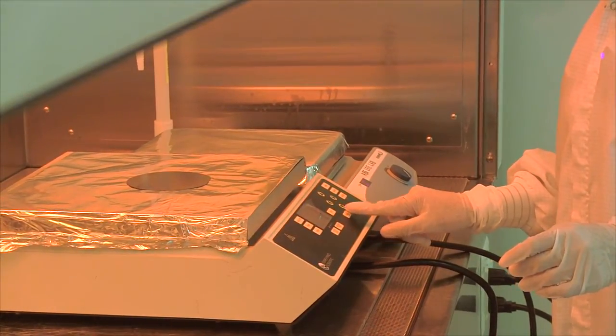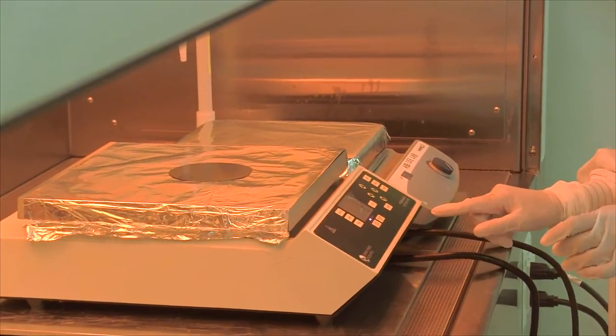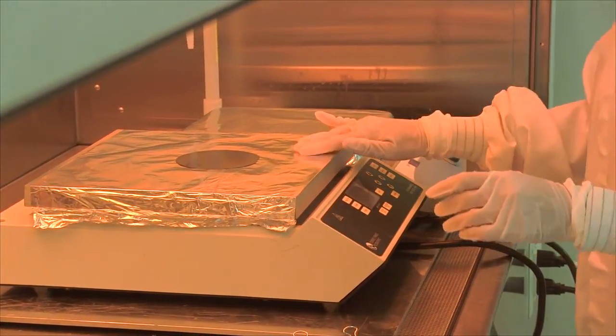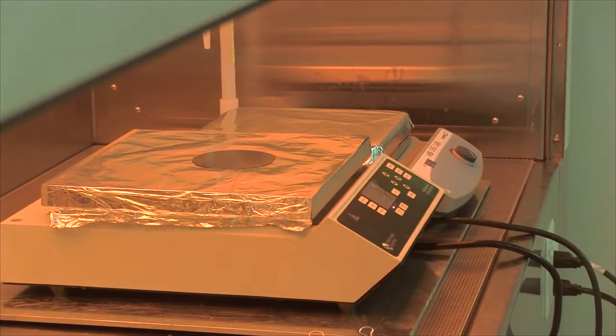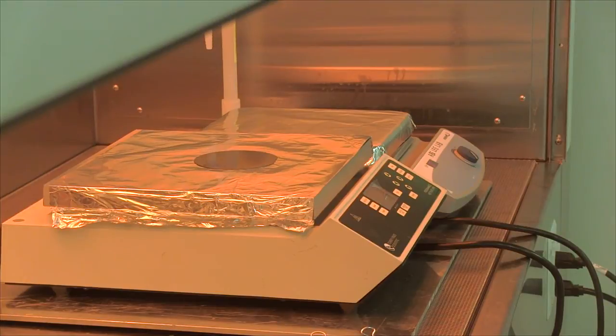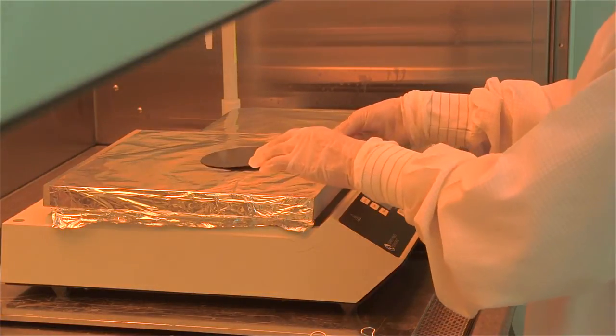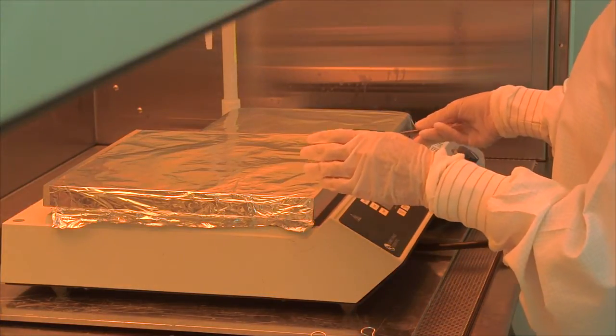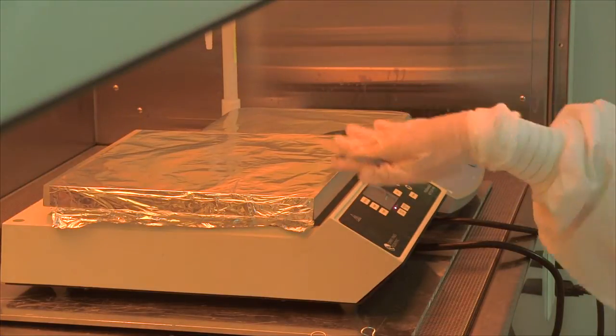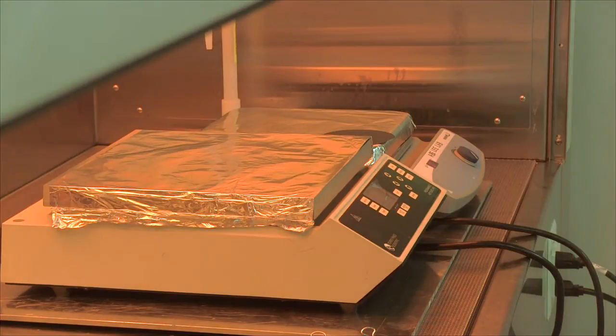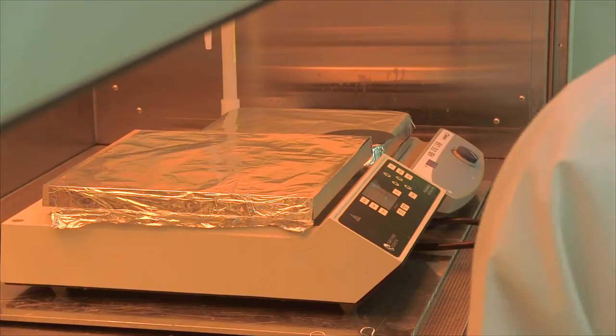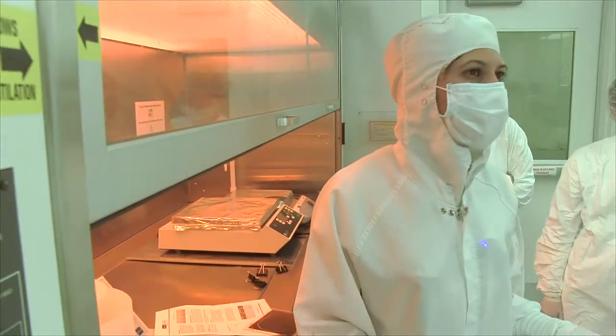It's still too hot. Okay, the hot plate still shoots up every time it overheats. I just want to make sure that it's done at the right temperature. So I'm just removing it from here for a few minutes because the hot plate is still at 70. I want it to come down to 65 because this is an important step, the post-exposure bake. For the soft bake, it's still fine if the temperature is 70 instead of 65 because you're just evaporating the solvent.